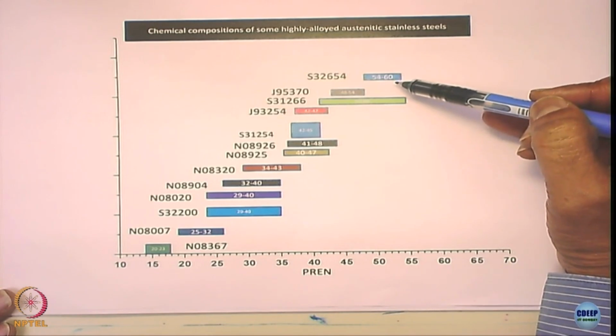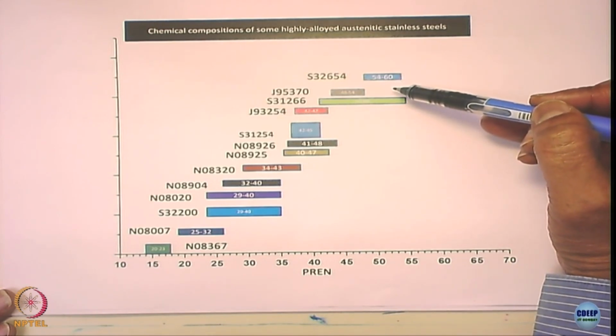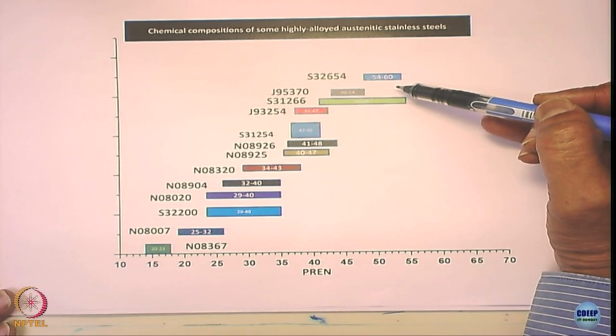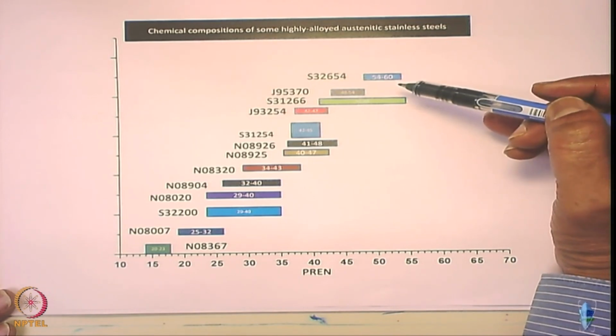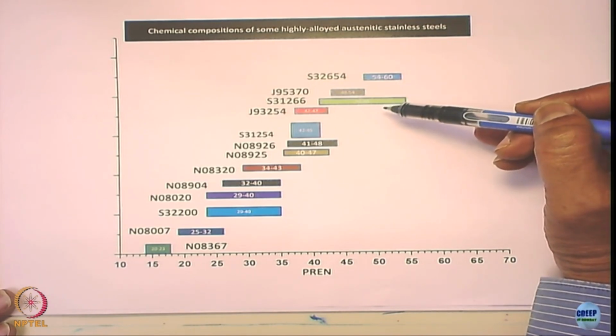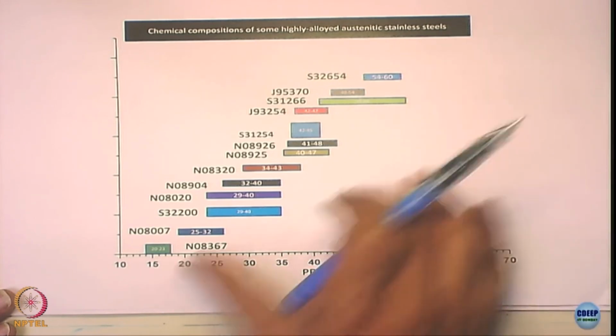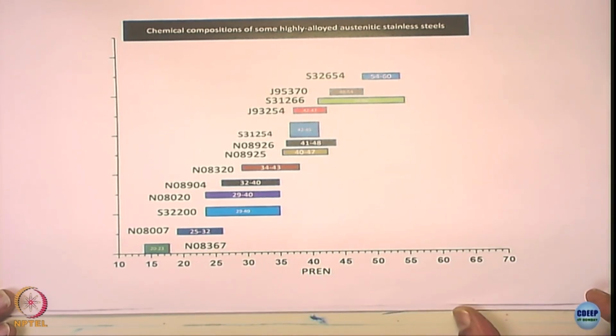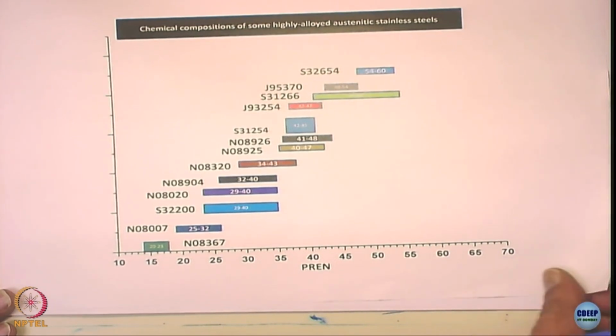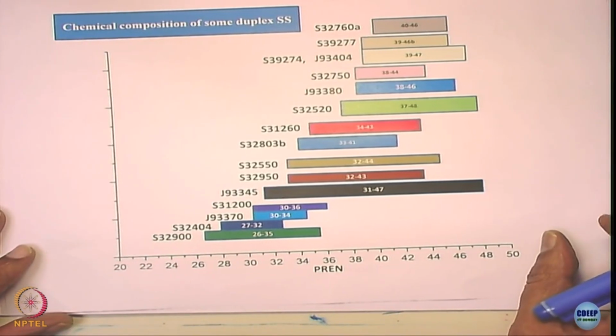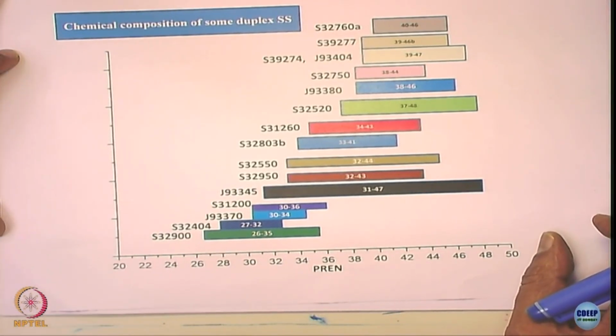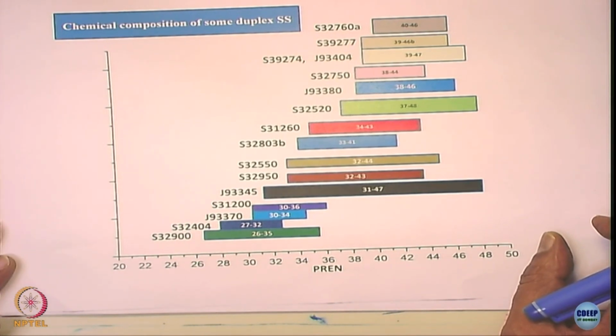higher pitting resistance, which means they have a higher PREN number, but the cost also goes high, right. You have more nickel, more molybdenum, and that really increases the cost. So that is one of the problems of using austenitic grade stainless steels. So what happened was that there is a variation of this. People use what are called duplex grade stainless steels. It's somewhere in between, and nickel based alloys also have very high pitting resistance.